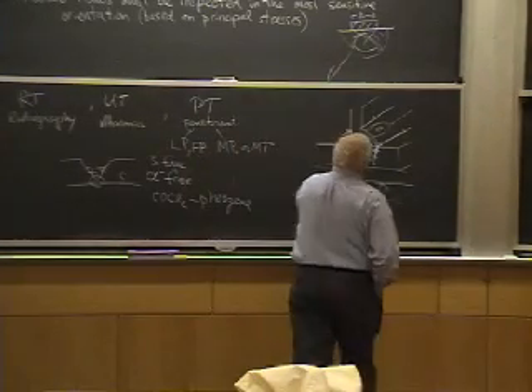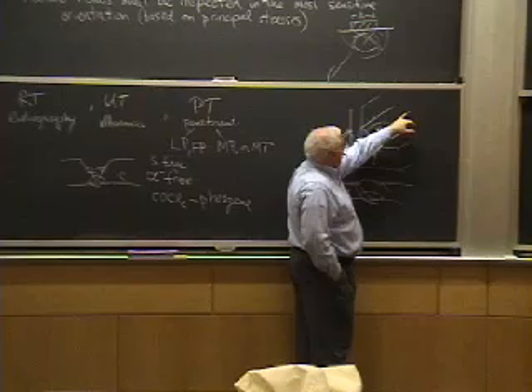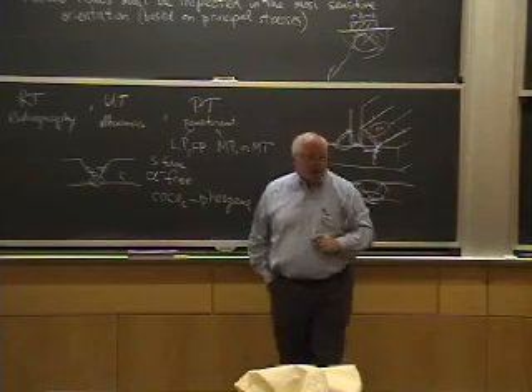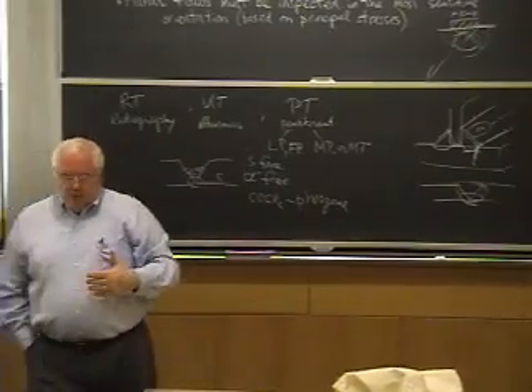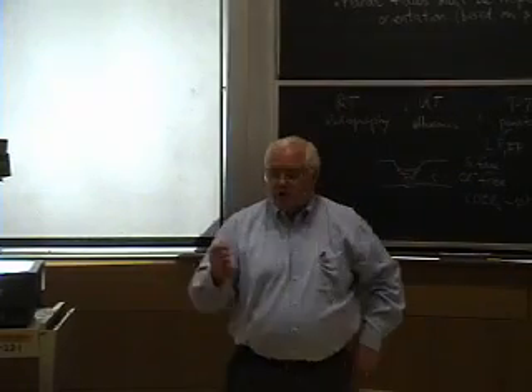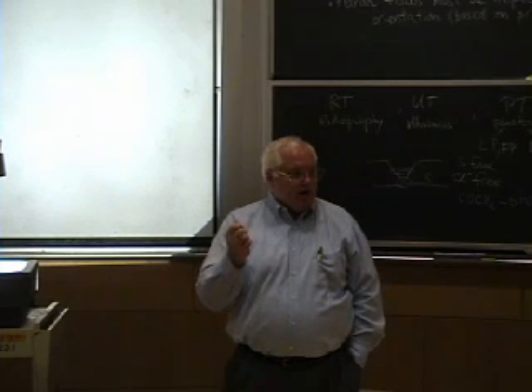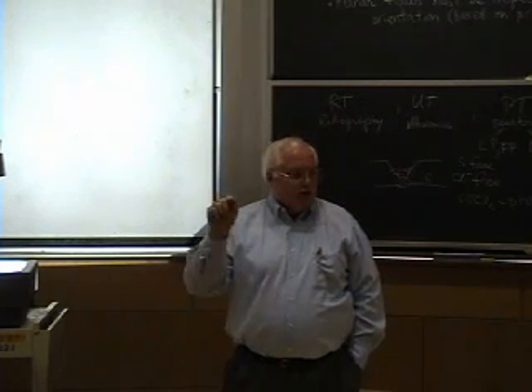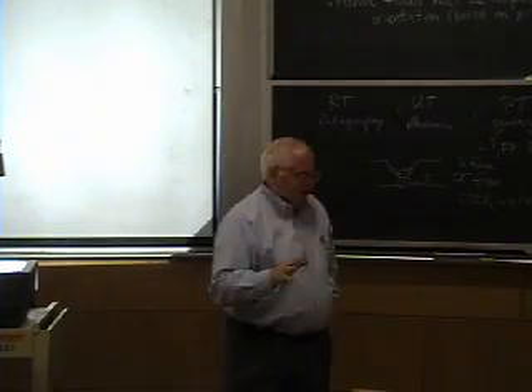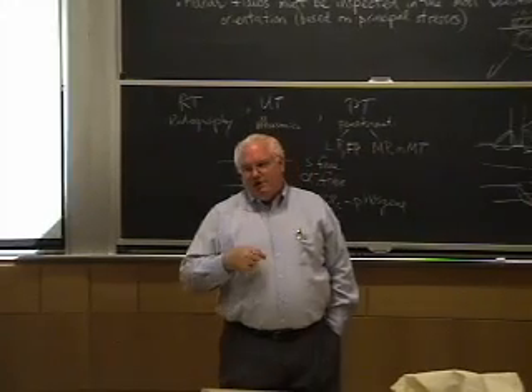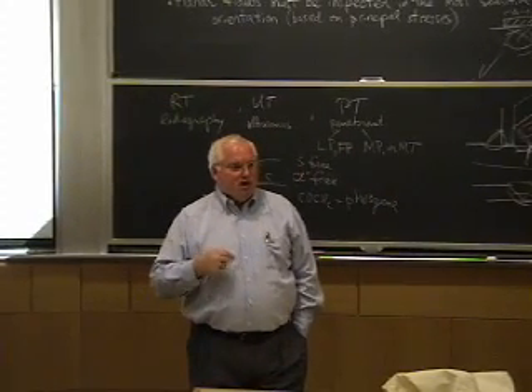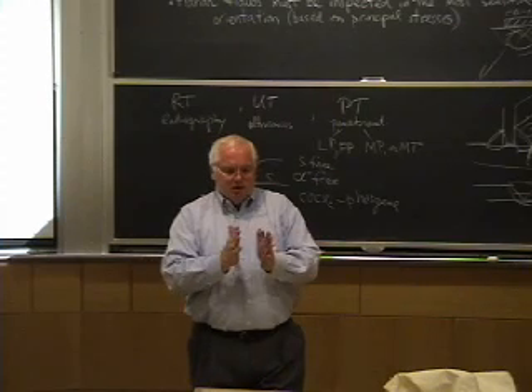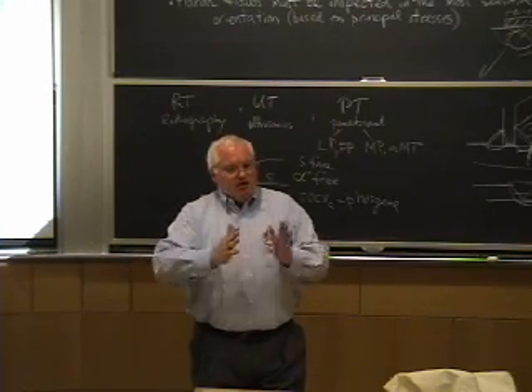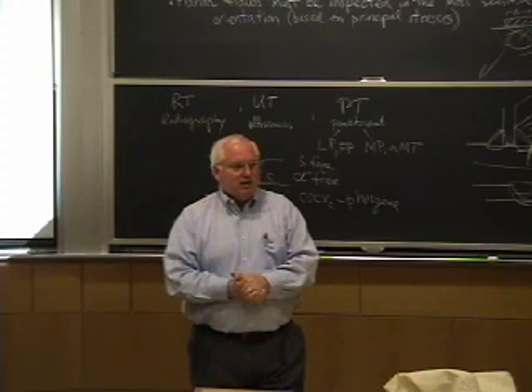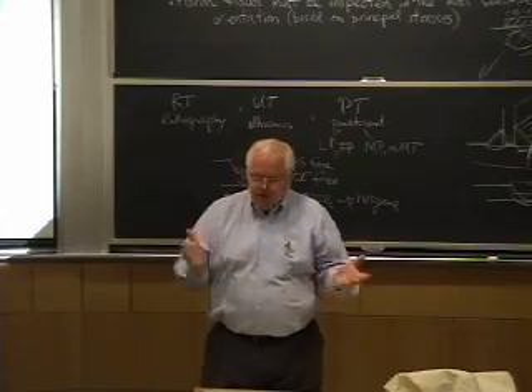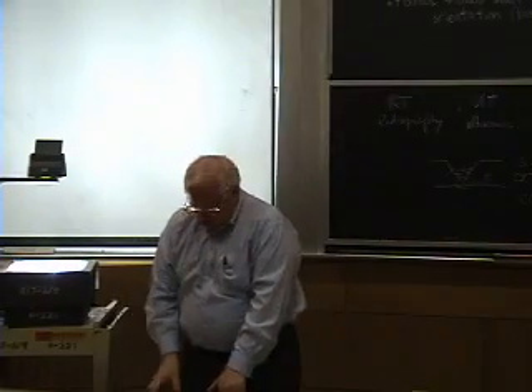So if you're welding structural aluminum, you're doing penetrant testing, yeah, you're going to look for toe cracks, but you're also going to look for centerline cracks, and you're going to look for crater cracks at the end of the welds. It turns out that with experience, people come to know where to look for flaws, just like I talked about inspection. If you're looking for a flaw and you have to go with a 10x magnifier to look for really small flaws, you have to tell the person where the hot spots are, either from a stress analysis or experience. Well, experience tells us that 90% of the defects in arc welding occur at the stop-start locations. So the stop-start locations are probably only a few percent, probably less than 5% of the total length of the weld, but they constitute 90% of the defects. Just because the heat flow and everything else is non-uniform, it's a transient condition, and it creates all kinds of problems.